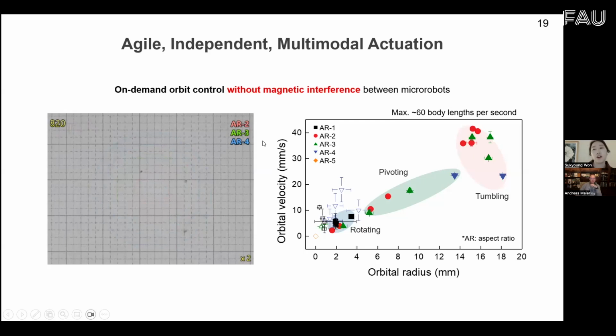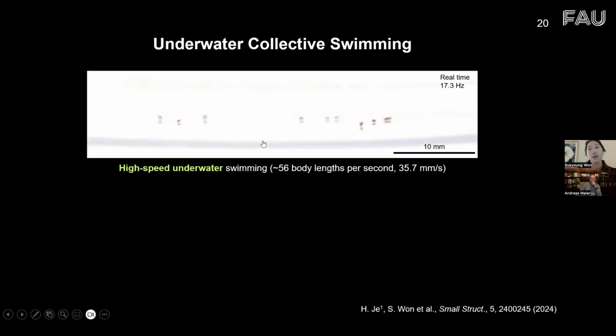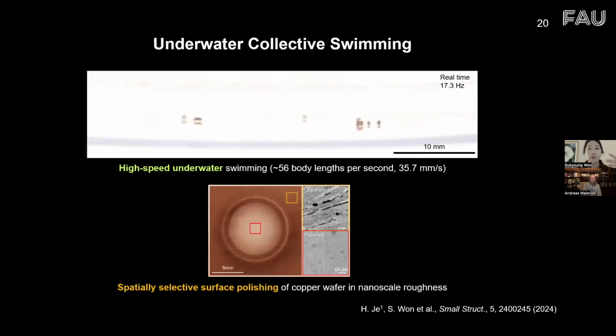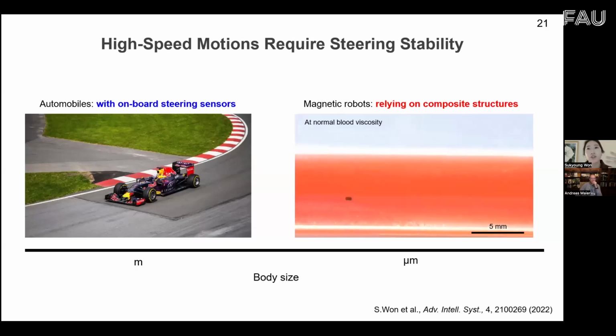These robots could even demonstrate collective swimming underwater at a really high actuation speed of 56 body lengths per second. And using this high-speed collective swimming behavior, we successfully demonstrated the nanoscale surface polishing of the wafer using the abrasive silicon nanoparticle solutions. However, for this high-speed actuation, steering stability is also really crucial.